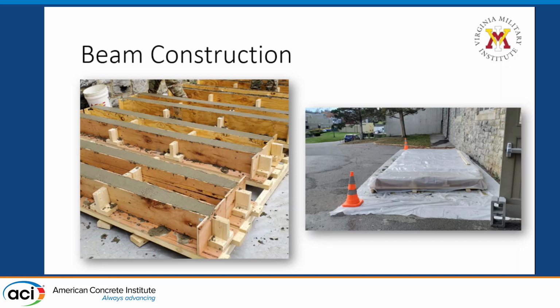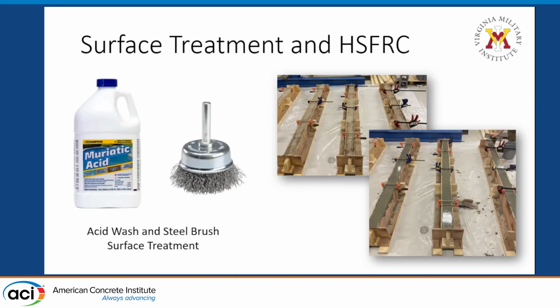We put them in the frames, and then once they were cured, we had to surface treat the faces of the beams that the laminate would be applied to. And this was done using muriatic acid and a steel wire brush. The acid would dissolve the cement paste at the surface of the face that we desired the laminate to be applied to, and the steel wire brush was used to flick away and roughen that surface. Here's a picture of the beams before laminate application and after.